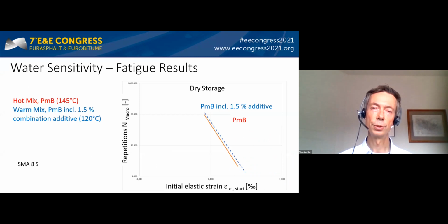This diagram shows the fatigue results for the dry stored samples. We plotted the number of load repetitions until observed macrocracking over the initial elastic strain. We see that the fatigue functions were equal with slight benefits for the Warmix. The Warmix is shown in the blue dotted line.